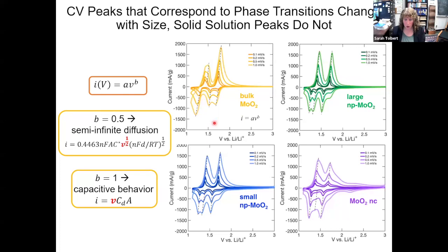So in the bulk, around the phase transition, we find that our exponent is pretty low, 0.69. As we decrease the size of the material, this exponent gets steadily closer to 1, moving all the way up to 0.93 in the smallest sample. If we look in a region where we don't have a phase transition, all of these materials show really high exponents.